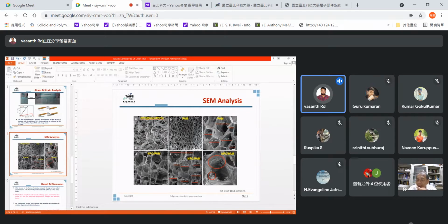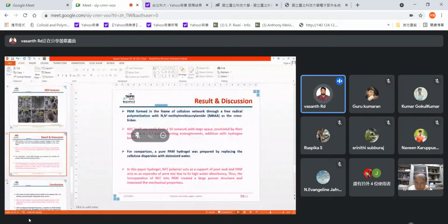the figure 1 shows the NFC, and figure 2 the PAM, in which the NFC PAM layer has more pores compared to the ordinary PAM layer, in which the pore size has been increased to about 100 micrometers, as you can see from the same images.